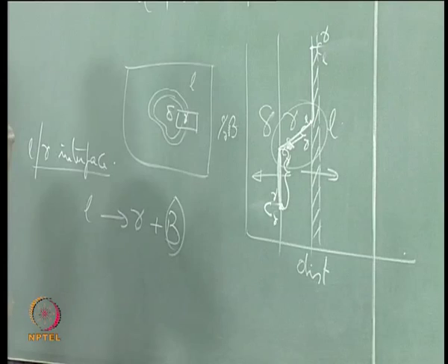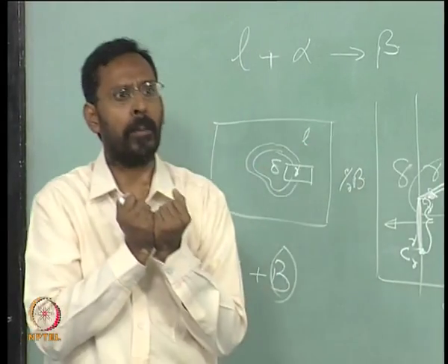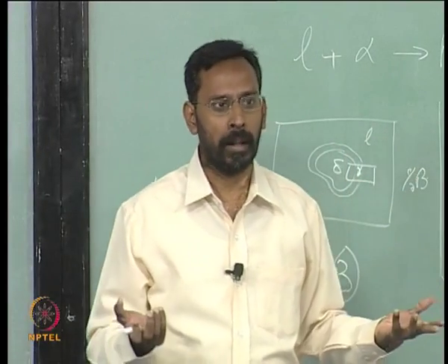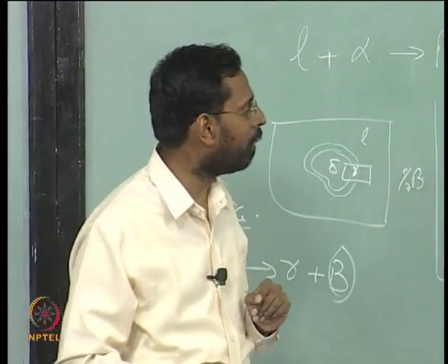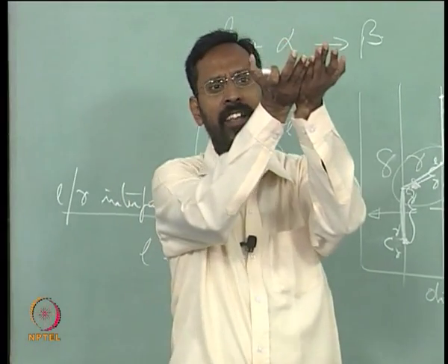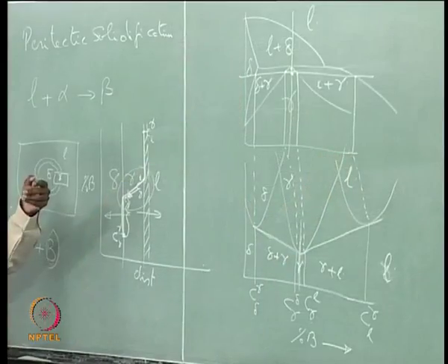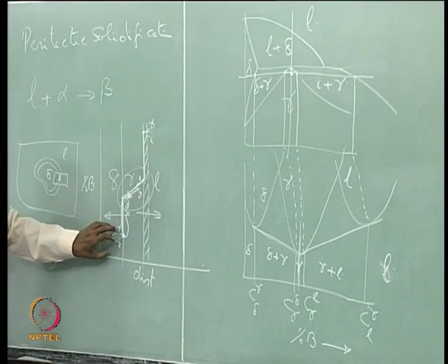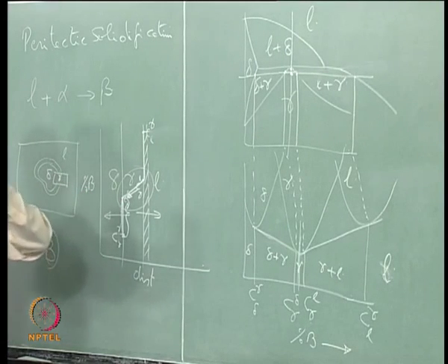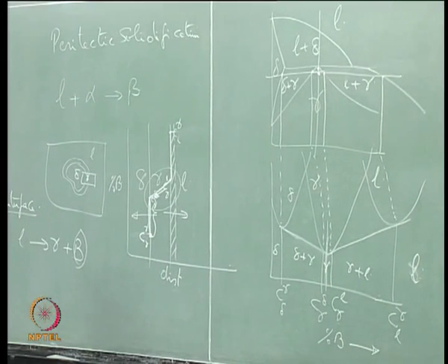So, if the delta takes B atoms, delta has a certain structure. In our particular phase diagram, delta has a BCC structure. This BCC structure takes in carbon atoms, in our case B atoms means carbon atoms because we are talking of the iron carbon phase diagram. So, this delta takes carbon atoms, and the carbon content in the delta rises to that of the gamma at that particular temperature according to the equilibrium. The moment the carbon content of the delta reaches that of the gamma, suddenly that particular delta gets converted into gamma. It is only a structural transformation now.